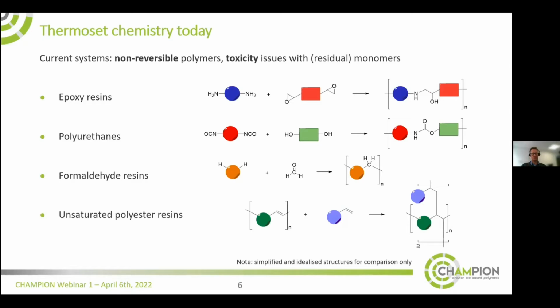If you look at thermoset chemistry today, you see a few main types of chemistries that are being used. One of them is called epoxy resins. And to the right, you see a schematic depiction of the chemistry that's involved. So for epoxies, you need amines. So you take amines and you react them with compounds that have multiple epoxy groups. And amines and epoxies react to form this polymer chain. In practice, this is a cross-linked network, but only the linear chains are shown for simplicity reasons.